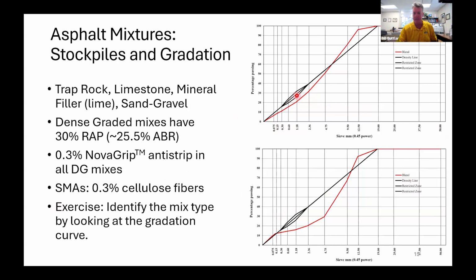The dense graded gradations were your typical below the restricted zone, below the max density line here at the critical control sieve type blends. And then those were 12.5 nominal max. And we also had a 12.5 nominal max SMA with that characteristic gap gradation. These had anti-strip and fibers in them. We went with 30% wrap, yielding 25.5% asphalt binder replacement. The control section was what the contractor already was doing and wanted to do. And the contractor was wanting to use less wrap, I think 20% wrap. So the control section we didn't modify.